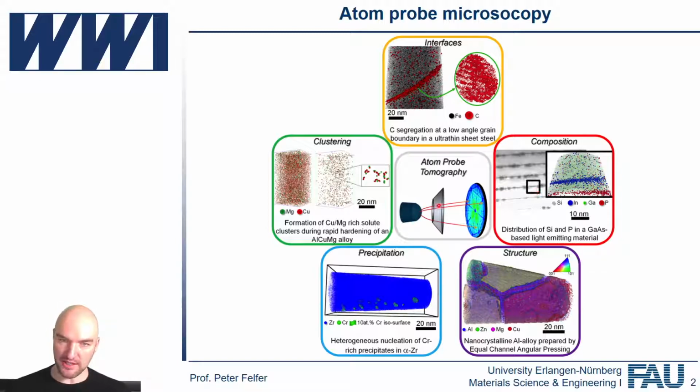But we don't just let them fly at any random time. We let them depart at very specific times. So we need to have a time we can correlate our ions to, and we have a time-resolved detector. And this is what allows us to identify which atom is which by the time of flight. And we're going to certainly hammer that home a couple of times during today.